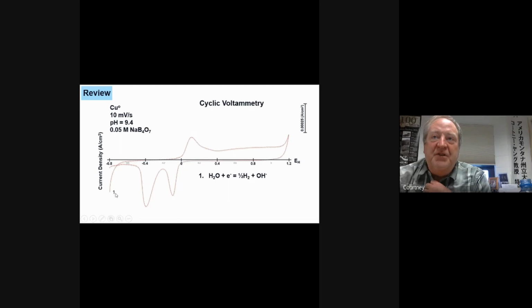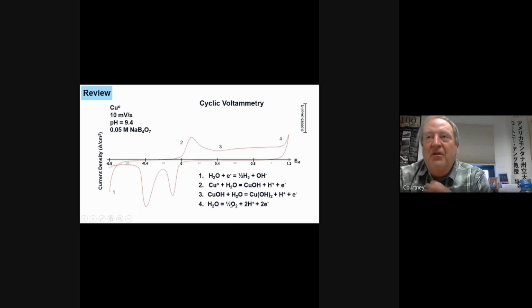And so we start here where reaction 1 is occurring, and we get hydrogen gas evolution. This is not a surprise. And then as you scan, you go through a zone here where there is no current. Of course, this is where copper metal is stable until you reach about an Eh of 0. And then you see this peak. And that peak is where you form copper(I) hydroxide. And then you get to a second peak in here where you start to see a little bit more current flowing. This is where you form copper(II) hydroxide. And then, of course, you get way out to 4 here, and that's oxygen evolution. Okay, no surprises.